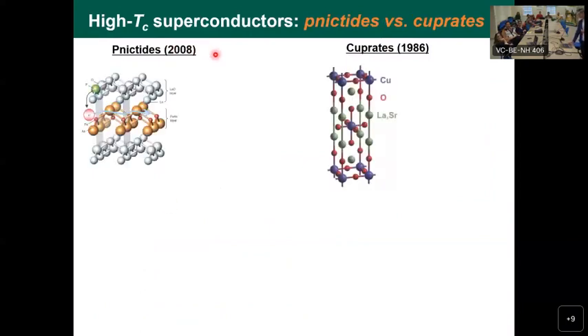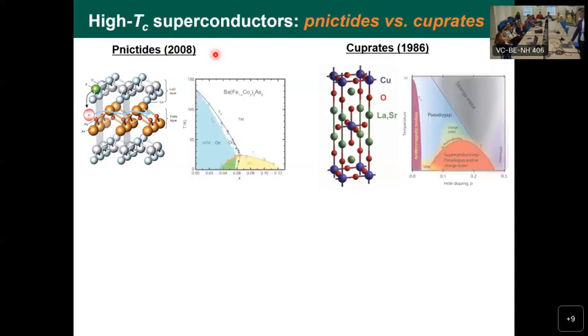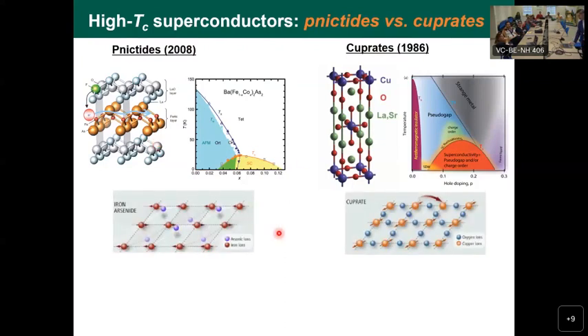The first thing you want to do is to compare with the previous family, which is the cuprates. Starting from the crystal structure, they have a very similar crystal structure, a layered one. A very similar phase diagram means this superconducting dome and antiferromagnetic order and so on. I will skip some details here. And the plane that hosts superconductivity is the iron arsenic plane here, and the copper oxide plane here. So there are some similarities, and actually the antiferromagnetic order is the main thing here.